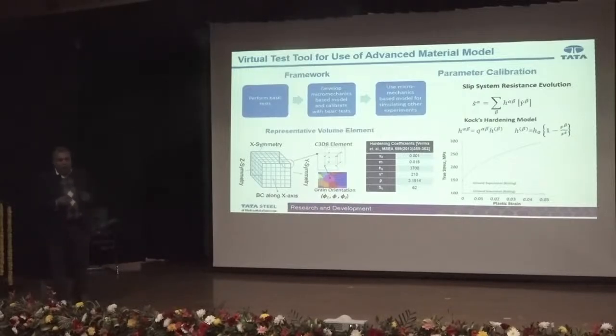Now, how do you do that? So one way of doing that is you start doing crystal plasticity based finite element analysis. Now, what is this? So we actually start doing the finite element deformation modeling of individual grains. The process is very simple. So suppose you have a chunk of grains, say 1000 grains, orientation you can actually calculate using EBSD, etc., and you can actually superimpose that.